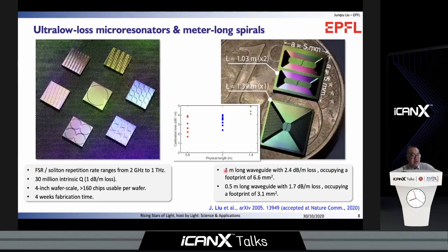This slide shows the summary of the microresonator performance fabricated using our Damascene process. Meanwhile, I want to also show you our progress on low-loss meter-long waveguides. Here I show the photo and the loss calculation data for half meter, 1 meter, and 1.4 meter long waveguides. For 1 meter, we can achieve 2.4 dB per meter loss.